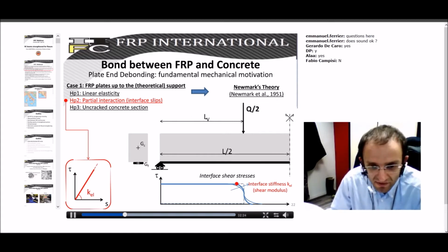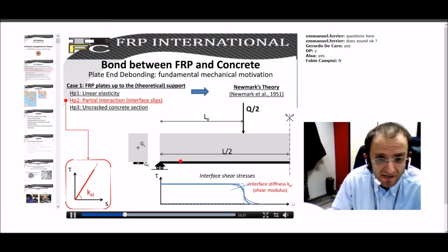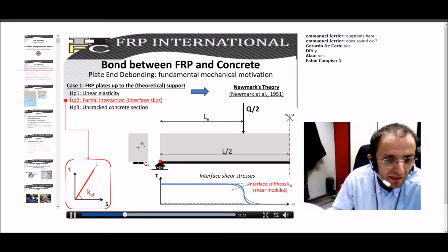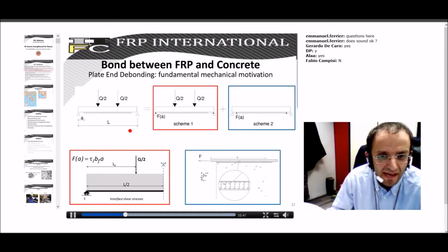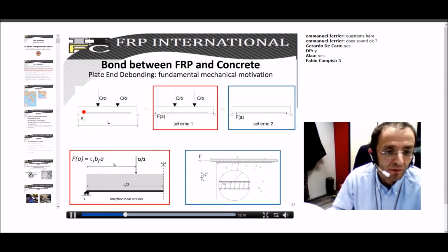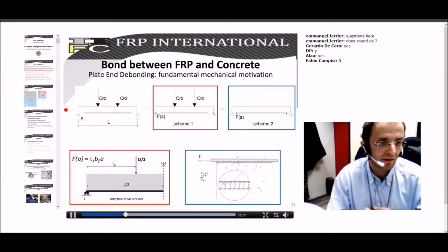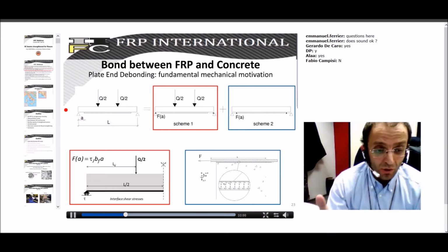So we have this distribution, but our FRP strengthened beams are not generally strengthened up to the theoretical support, because this is not technically possible, because here, for instance, you have a column, or you cannot access this position. Usually, FRP is interrupted somewhere at a certain distance, a, say, from the point. What is the consequence of this distance between the cutoff section and the theoretical support?